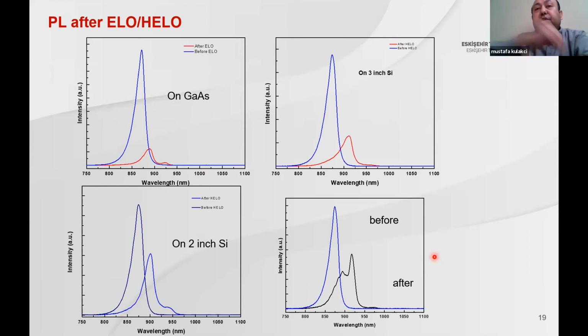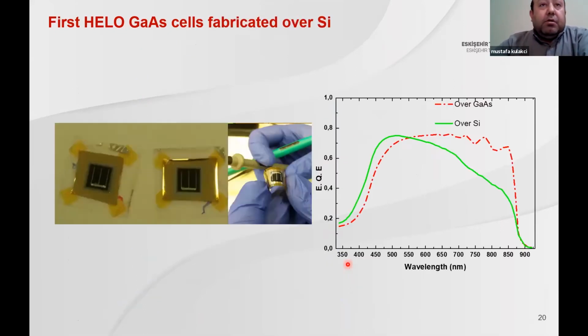Also, the important thing is here, you can easily see valence band splitting. Here, the degeneracy is broken in the valence band. This is a light hole and this is a heavy hole, which means that due to tensile strain over the surface of the devices, the band gap shifts to lower energy, and in some cases, depending on the strain on the devices, you can easily see the valence band splitting, which can maybe also be utilized for strain measurement sensor applications. And this is the first HELO GaAs solar cell fabricated over silicon.